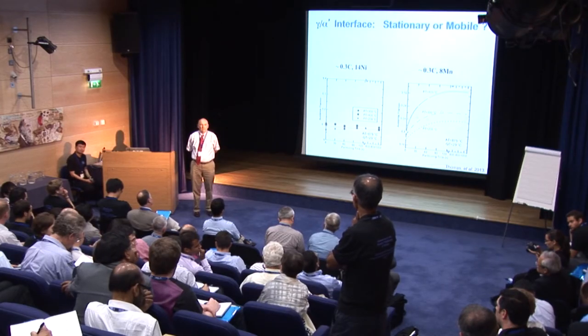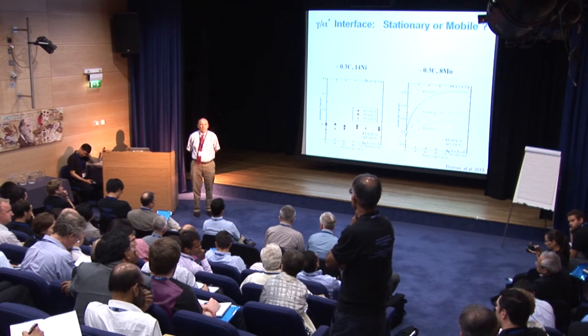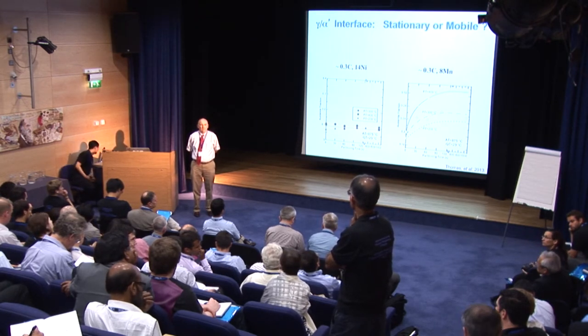And also what we have observed in carbide-free bainitic steels is that for subsequent low temperature temperings, at around the temperature where we get the epsilon carbides that you mentioned before, dislocations segregated with carbon can be a key issue. Because with time and temperature, Cottrell atmospheres will evolve into what we have seen as clusters, and after that will be the perfect nucleation site for an epsilon carbide. Then I wonder if you investigate your dislocation densities and the carbon trapped at those dislocations, you can explain the appearance or not of epsilon carbide or more or less retained austenite at the end in your microstructure.